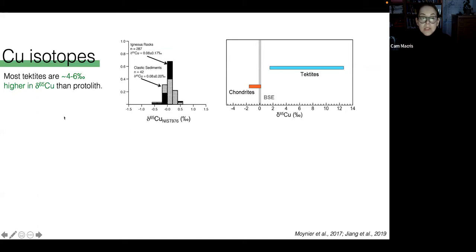It turns out most tektites are about 4 to 6 per mil higher in delta 65 copper than their proposed parent materials. This histogram shows the range of variability in all igneous rocks and clastic sediments as relative frequencies, both hovering at about 0.08 per mil, which agrees well with that of the bulk silicate earth, plotted as the gray bar on the plot on the right, showing the delta 65 copper variability in chondrites and tektites. We can see in this plot that tektites range from about 2 up to about 12 per mil, although most are around 4 to 6 per mil. And they are certainly higher than their parent materials, which would be represented by the bulk silicate earth here.